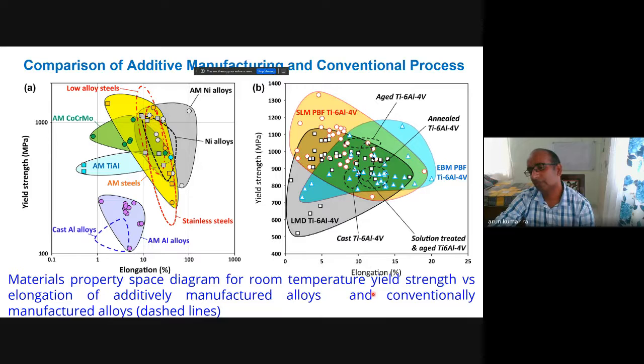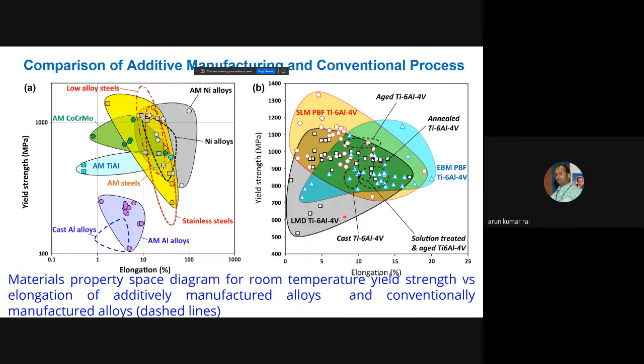Second thing you can see here is the same thing. This is titanium 6 aluminum 4. This is an aerospace material. You can see the cast structure has design property like this elongation and this strength, but you will see that additive manufacturing has covered a wide range of this. It can start up to here, ductility is also achieved, and even in the cast alloy, solution treated and aged also are limited to this. So additive manufacturing is covering the entire range by optimizing certain processes.